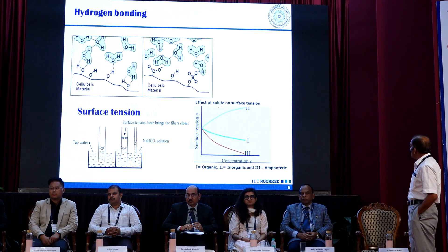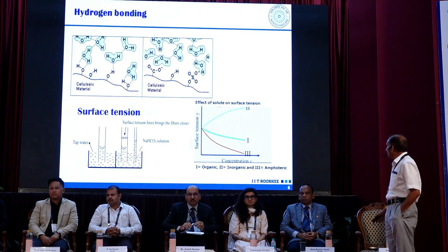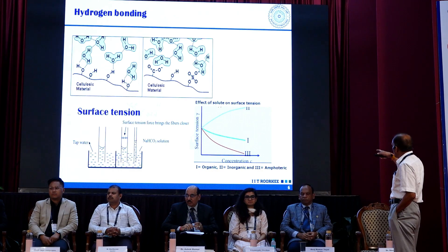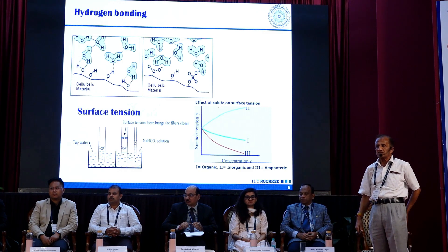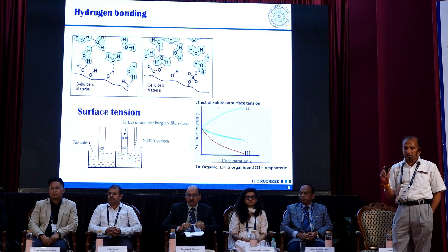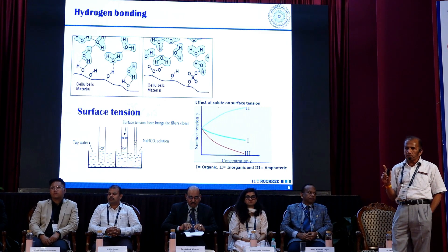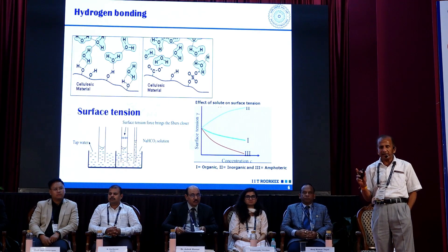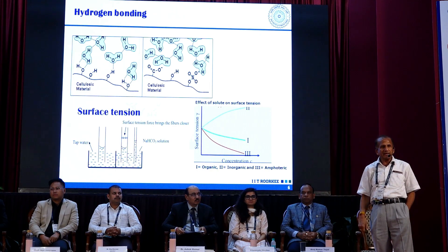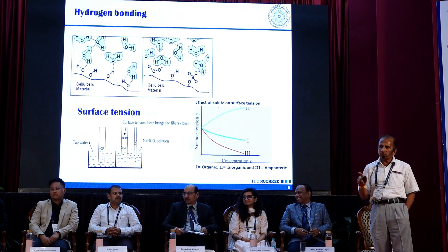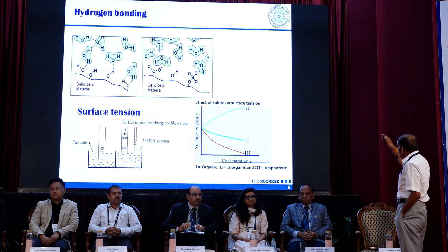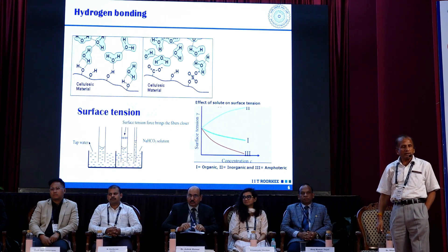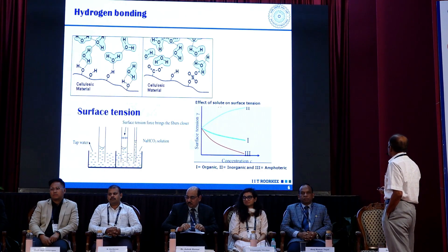This third graph is very important. We have three types of additives during the paper-making process: inorganic solutes, organic solutes, and amphoteric solutes. By adding inorganic solutes, we can increase the surface tension forces during the paper-making process. If the surface tension forces increase, then the porosity will increase and at the same time the water absorption (Cobb) value will increase. For example, in absorbent grade paper, if you simply add sodium bicarbonate, you can increase both the porosity and the water absorption property. But if we reduce the surface tension forces, then the Cobb value and porosity will both be reduced.